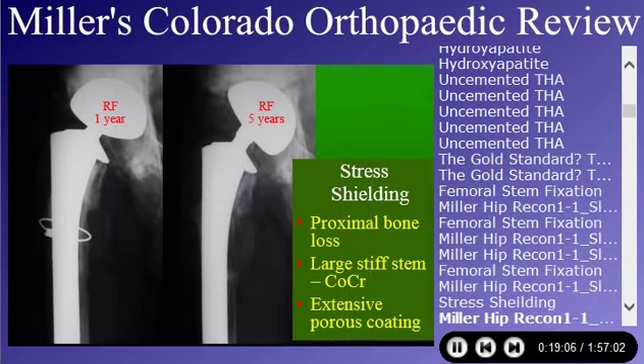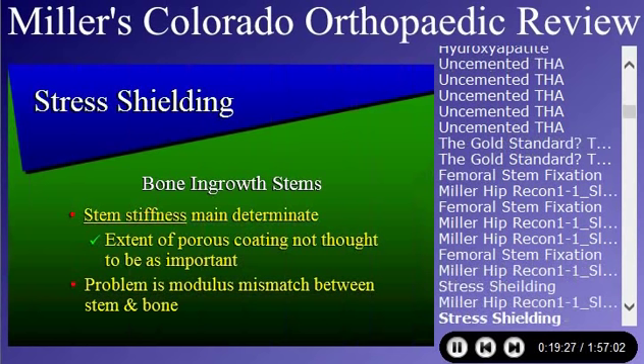The slide on the left is an AML stem. You can look at it at 5 years. You can see the amount of bone loss in that area. Proximal stress shielding represents proximal bone loss. It usually is associated with a large, stiff, cobalt chrome stem that is extensively porous coated. And if you look at the test questions, it turns out that stress shielding is more related to stem stiffness than it is the extent of the porous coating. Stem stiffness is the main determinant. Porous coating is not as important, but is a factor.